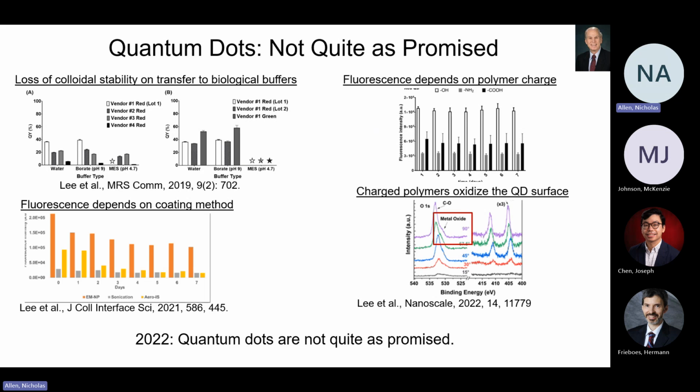And then we determined that that was because the formation is slower when you make them with charged polymers because of charge repulsion. The polymers don't want to come together as quickly. And that allows the organic particle to be exposed to the aqueous phase longer, which resulted in its oxidation. And when it oxidized, it lost fluorescence. And that was actually a mechanism of what was happening here as well. So it took me a really long time to figure all these things out. But we did. And this is partly why it was so difficult to commercialize this technology and bring this into a clinical market.